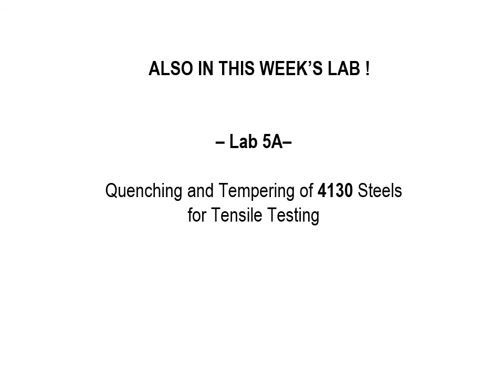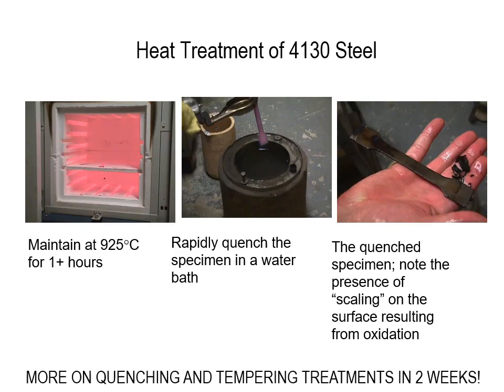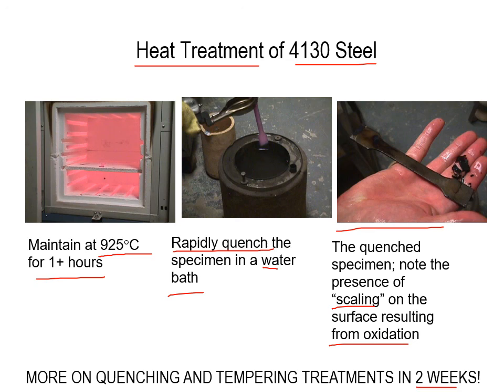So in this week's lab, we're going to be doing the quenching and tempering of the 4130 steels for tensile testing for our later lab in 5A. So we're going to talk briefly here on heat treatment of our 4130 steel. What we're going to do is heat this and maintain it at 925 degrees Celsius for a little over an hour. Then we're going to rapidly quench in a water bath. If we take a look over here on the right in this image, the quenched specimen, we can note that there's a scaling on the surface resulting from oxidation. Now we're going to talk more on quenching and tempering treatments in a couple of weeks when we get to our next lab, Lab 5.